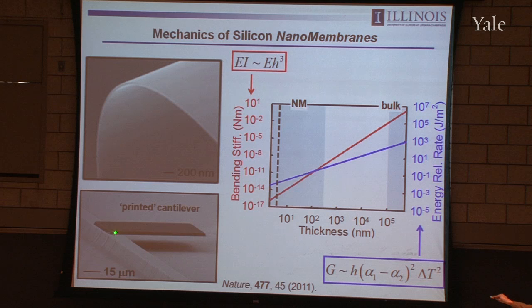No adhesive here. It's just by virtue of van der Waals, very non-specific adhesion forces, that keep this piece of silicon tethered to the substrate at this one end, to the extent that you can keep this other part of the silicon suspended in a kind of cantilever fashion. And the reason why the membranes stick so well to other materials has to do with the fundamental properties that drive crack propagation between two materials that you bring together in this way. And in particular, the propensity for forming cracks, if everything else is held the same in the same geometry, increases linearly with the thickness of the material.